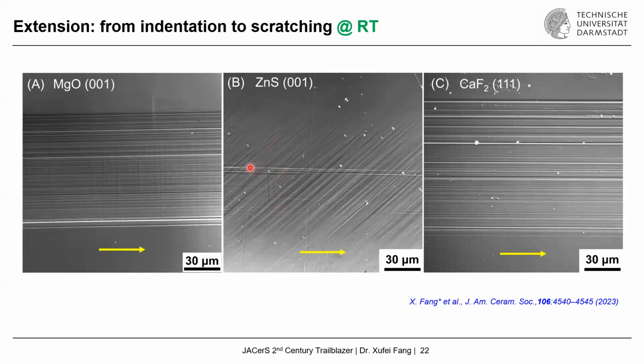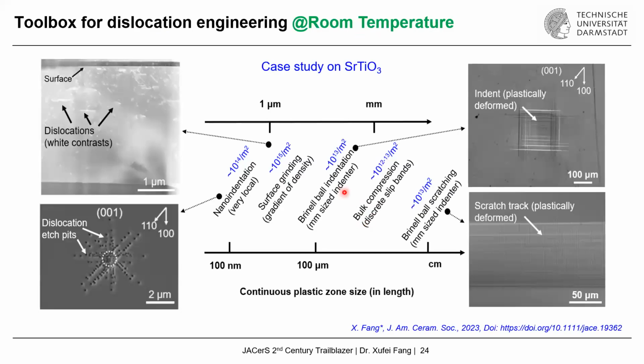Of course, again, we extend it to other material systems, for example, magnesium oxide, zinc sulfide, and calcium fluoride, etc. So we really can see the general applicability of this technique, the cyclic indentation, also stretching, for generating a much, much larger plastic zone and also a much higher dislocation density. Just to quickly summarize, this is the toolbox that I briefly mentioned at the beginning. Across the length scale, we are able to generate plastic zone sizes of hundreds of nanometers with the nanoindentation technique at the very beginning, and now even up to centimeters in length. And of course, we can tune the dislocation densities as well, even up to almost 10 to the power of 15 per square meter.